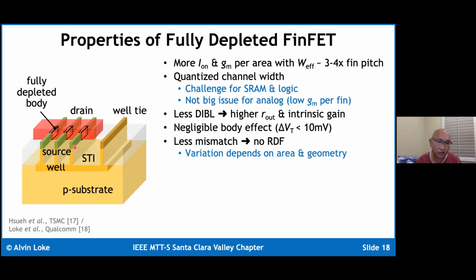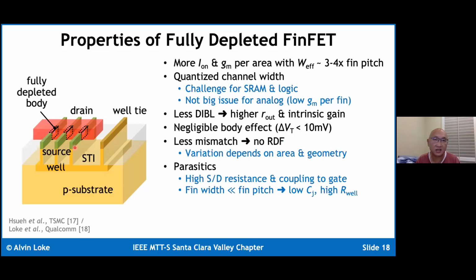Okay, the mismatch is less in these devices because we're not really counting on doping or implants. We are less prone to random dopant fluctuation, but then we still see variation being very heavily dependent on area and geometry. Okay, parasitics is what we have unfortunately picked up by having the structure being very, very tight together. Basically, with a tight three-dimensional structure, the source drain resistance is very high, meaning that the source degeneration is a serious problem, and the coupling of the contacts to the gate, the source drain to the gate, is also very high.